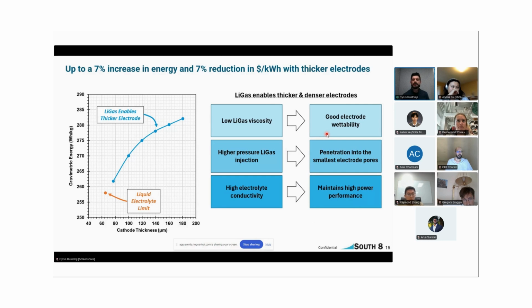So a few other areas that we are looking to increase energy: silicon, of course, but also going to thick electrodes is really interesting to us at South 8. We believe we can offer a 7% increase in energy and a 7% reduction in dollars per kilowatt hour with thicker electrodes. So why can South8 enable these thicker electrodes?